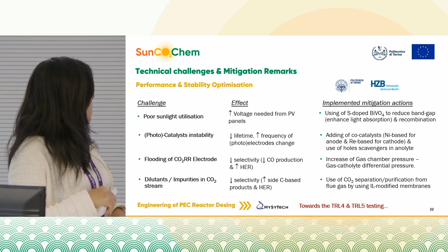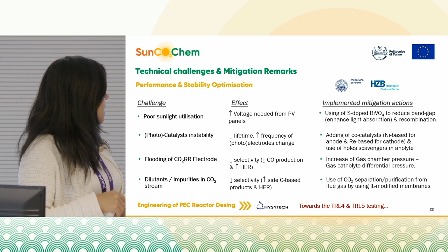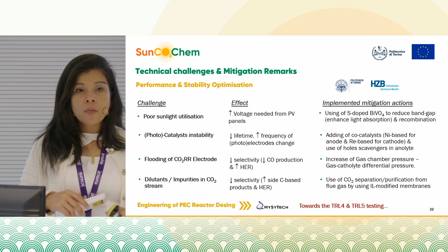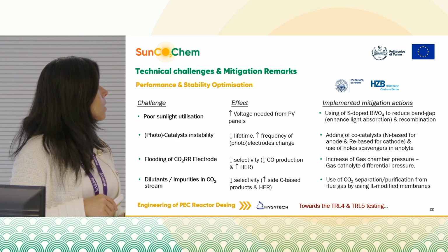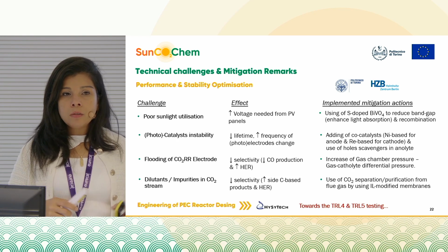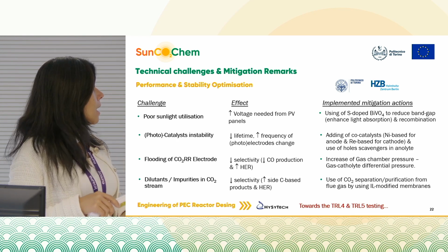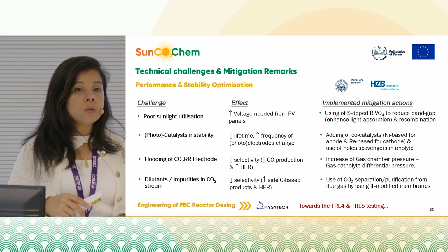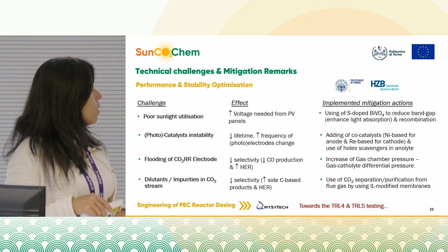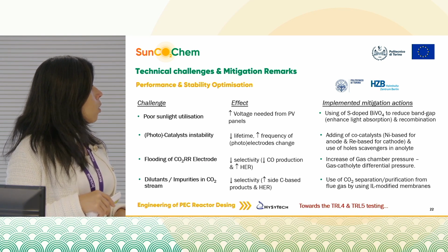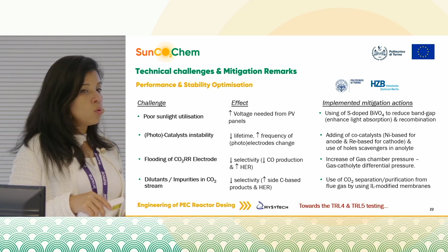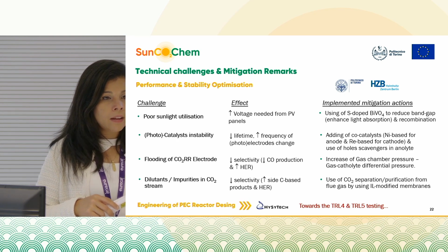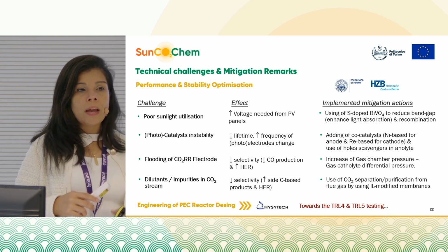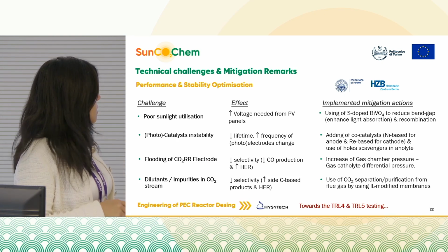To face and mitigate the challenge regarding the instability of the catalyst and photocatalyst, we added some co-catalysts to our electrodes, so nickel oxide, for example, in the photoanode, and rhenium-based molecular catalyst in the cathode. And also we had to use hole scavengers in the anolyte in order to enhance the kinetics of the process.